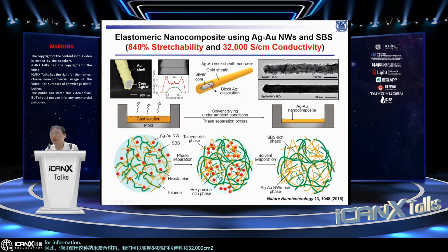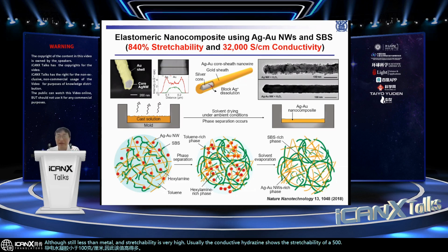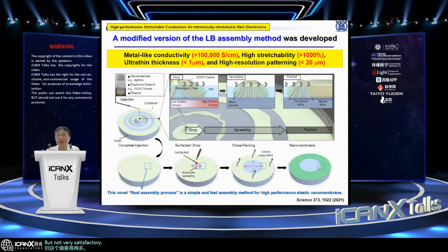For information, the conventional typical conductivity of the conductive hydrogel is less than 100 siemens per centimeter. So this value is much higher, although still less than metal. And the stretchability is very high. Usually, conductive hydrogels show a stretchability of 500%, something like that. But this value is much higher. But not very satisfactory. As I mentioned, we want to make high-performance intrinsically stretchable skin electronics. And in that case, we do not want to sacrifice the electrical performance of the device.